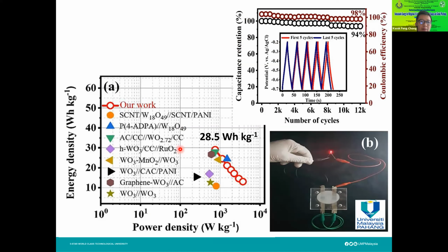If we compare to the rest of the hybrid materials which use tungsten oxide, for this material, the tungsten oxide mixed with the graphene, we found that it actually possesses the highest energy density stored so far. It also has very high stability, whereby this device can be charged and discharged for up to about 12,000 cycles. That is different from your cell phone lithium-ion battery. Lithium-ion battery, normally you can charge it up to 1,500 or 3,000 cycles. I think it's a limitation for the lithium-ion battery. But for this, we are able to charge and discharge it up to 12,000 cycles.